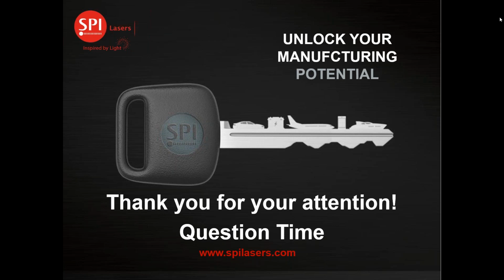Okay, there's also a lot of articles. Sorry, I'm just reading this. There are a lot of articles where green and even blue lasers are being used as the best laser source for welding copper because of the lower reflectivity or higher absorption by copper. Okay, to some extent that's true. And you will see good processing samples generated by these people.